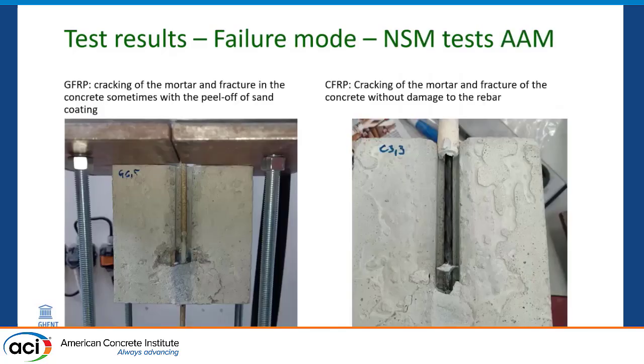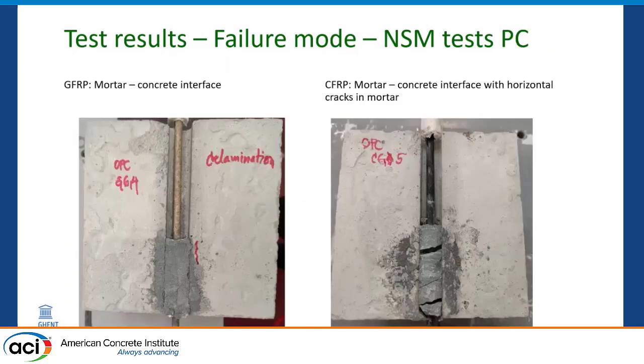So now I will jump to the failure mode of the near surface mounted tests. We can see here that the failure mode is cracking of the mortar with the fracture of the concrete and peel off of the sand coating sometimes for GFRP with alkali-activated mortar, and cracking of the mortar and fracture of the concrete without damage to the rebar for CFRP.